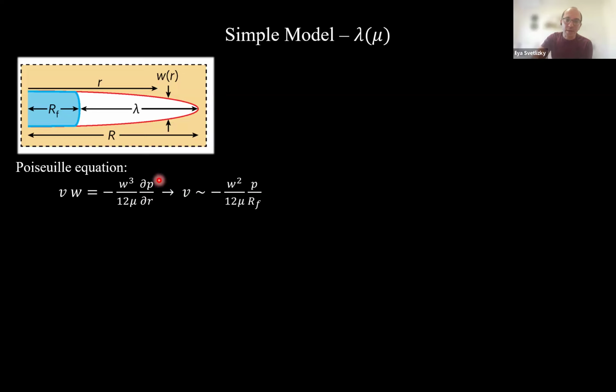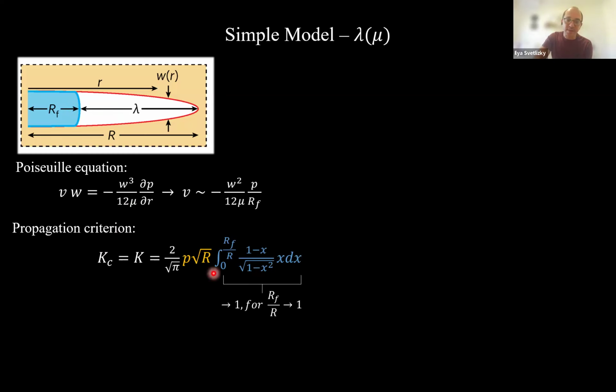You take your pressure to be linear with pressure, the gradient of the pressure scales like P over the radius of the fluid front. You again rewrite the stress intensity factor in some useful form where the integral is non-dimensional. So you have one part that increases linearly with P and an integrand that is monotonic, and it increases to 1 when the fluid front equals the radius of the crack. So RF divided by r equals 1, this integral goes to 1. You compare the stress intensity factor to a one value, Kc. Again, these are only 10%, so I'm ignoring any difference between initiation and the rest at this point.